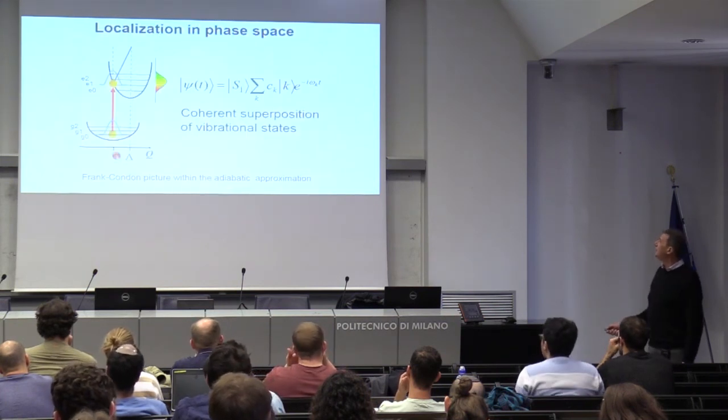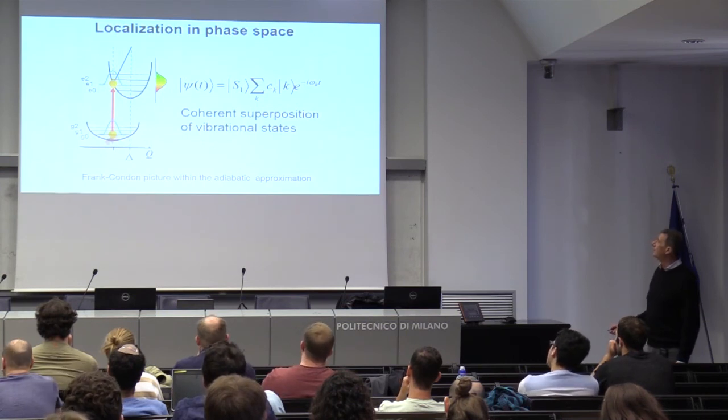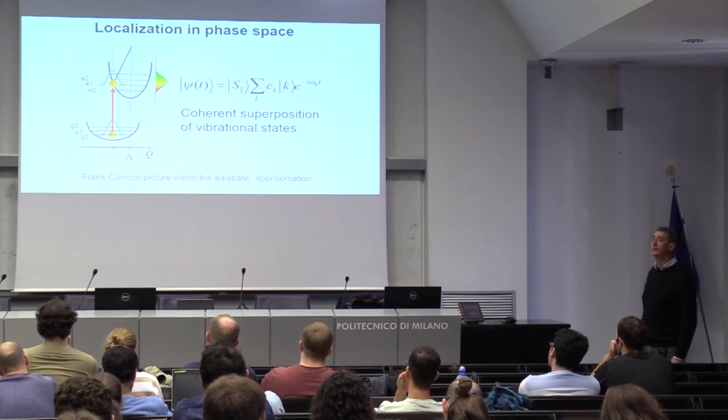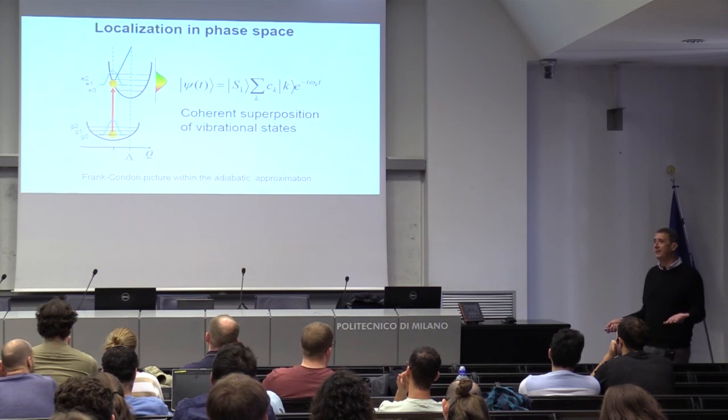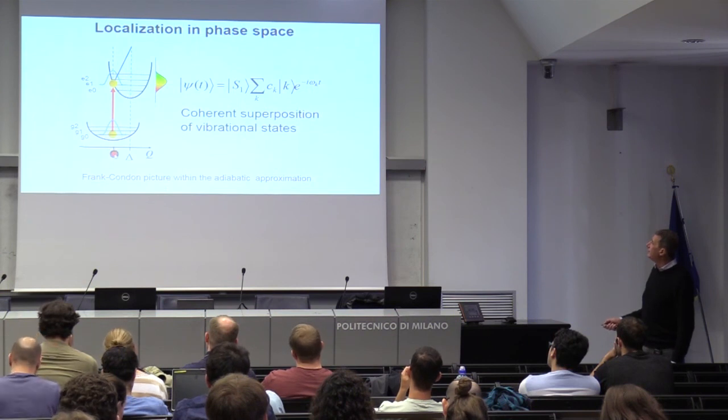Here you see the equation better. What we do is project the ground state wave function of the harmonic oscillator, a Gaussian, into the excited state, but in a different position. You see, I displaced the equilibrium position of the oscillator. And this displacement depends on the electron-phonon coupling. If the electron-phonon coupling is 0, there is no displacement, nothing is occurring. If there is electron-phonon coupling, the position here is different from the position here.